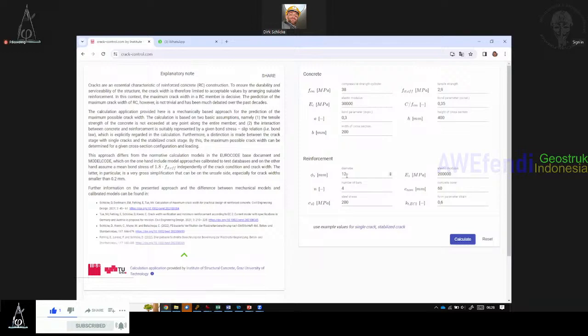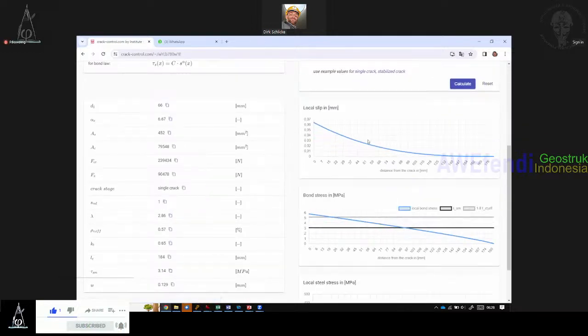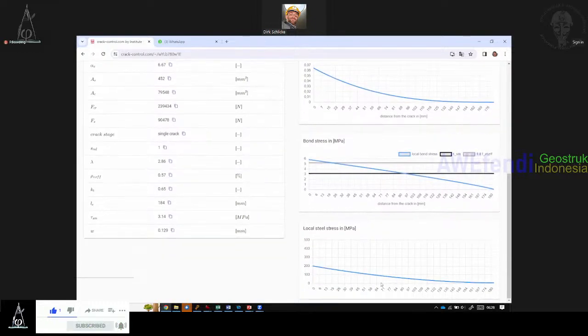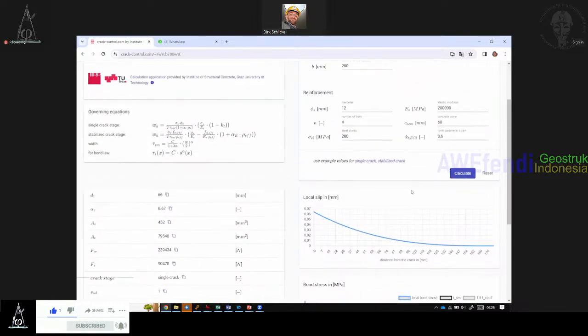we have 12 millimeter diameter, 4 bars. This is the steel stress we are going to calculate. And if you go calculate, as I showed, iterative solution, the homepage will do everything for you and gives you here now the local slip for the experiment. You see the bond stress evolution over the length. The black line is the mean bond stress. The gray line is the 1.8 fctm assumption, not very well fitting. And then you can see here the local steel stress. And the resulting crack width for this configuration would be 0.13. Also possible for stabilized crack stage.